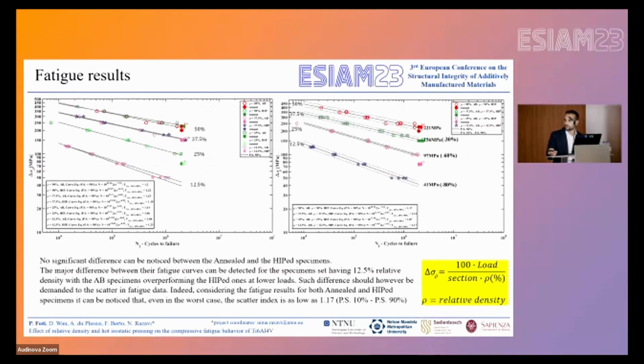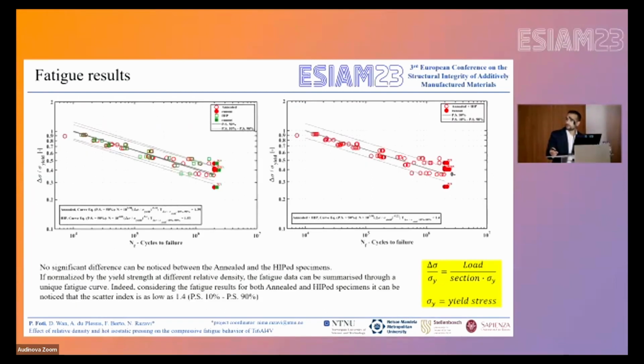The first solution that we thought about is to consider an effective fatigue stress by dividing the stress over the relative density. But as you can see here, we are still talking about a difference of about 80% with respect to the condition of 50% relative density. So this approach, of course, is not useful for our aims. But if we consider the yield strength of the different components having different relative densities, as you can see here, we are able to consider all the fatigue data that we achieved with the different relative densities through a unique fatigue scatter band having a scatter index of just 1.4.